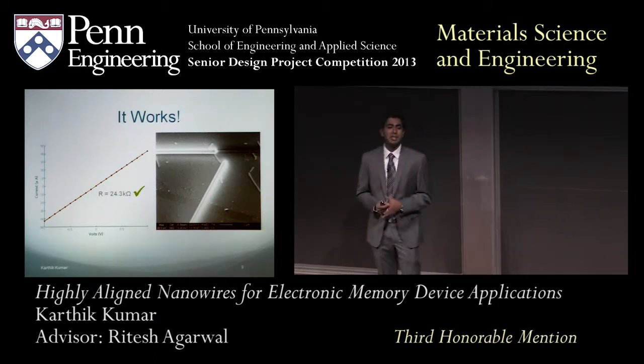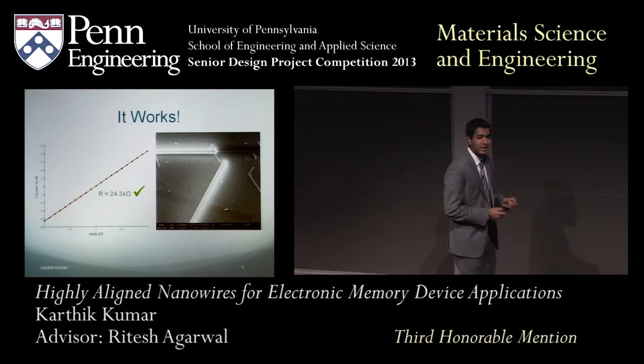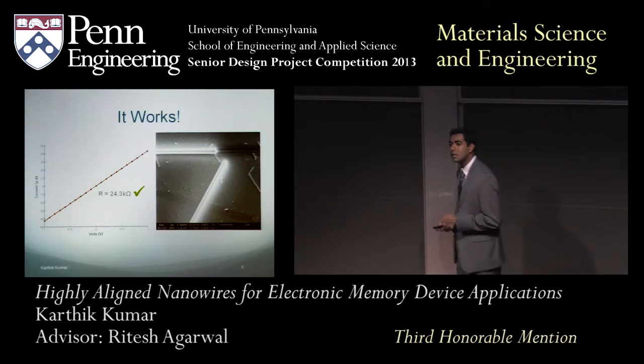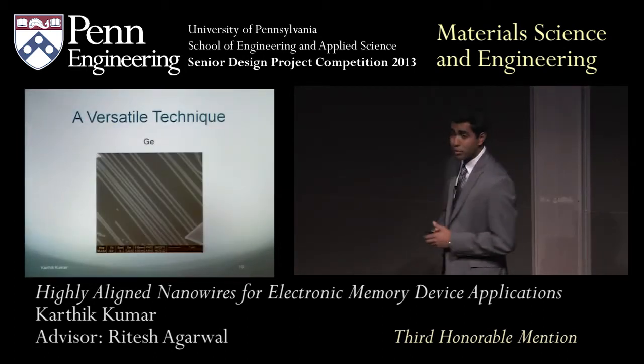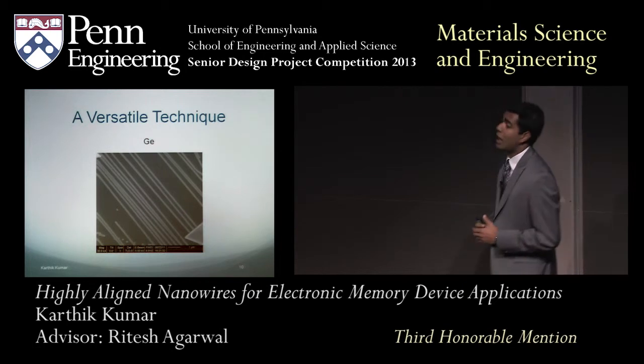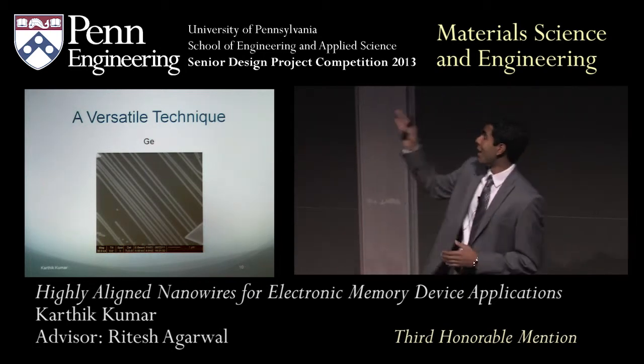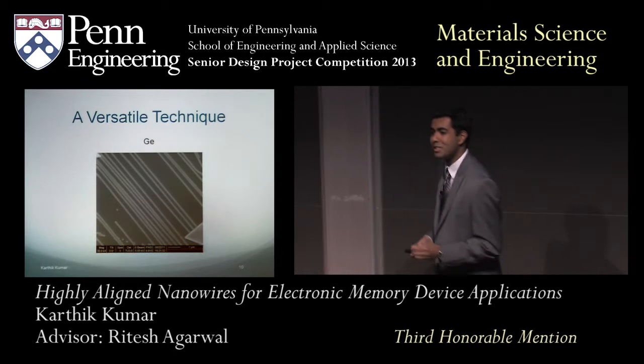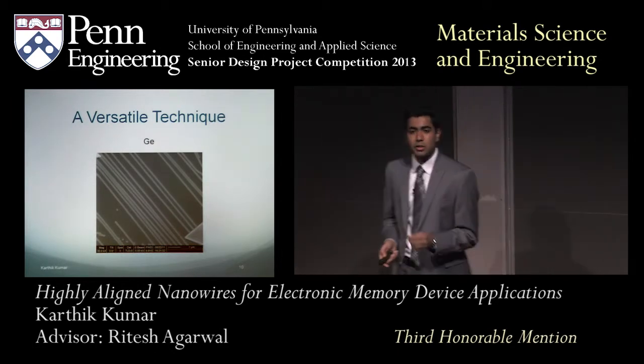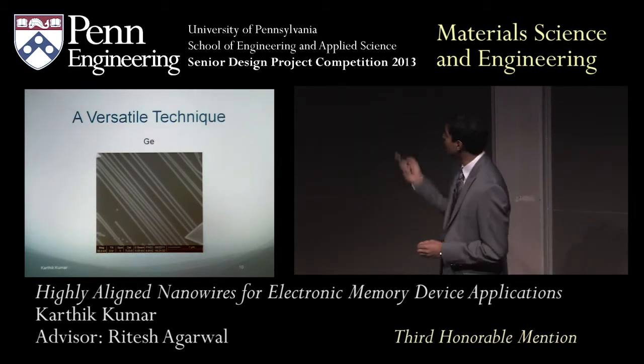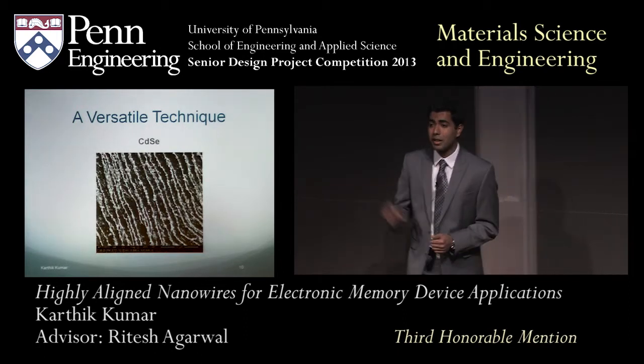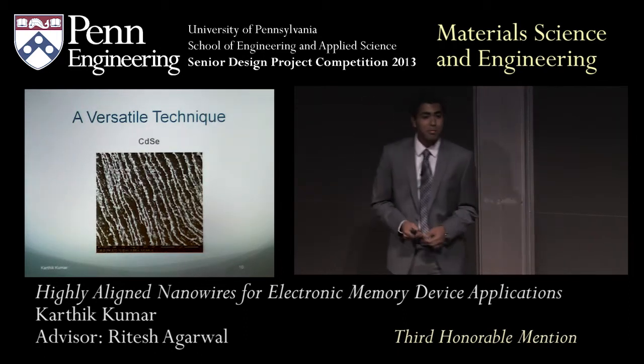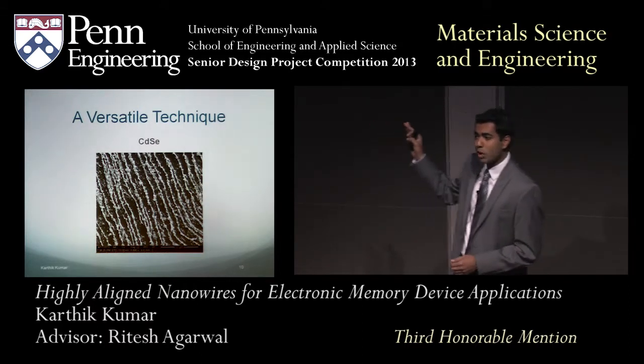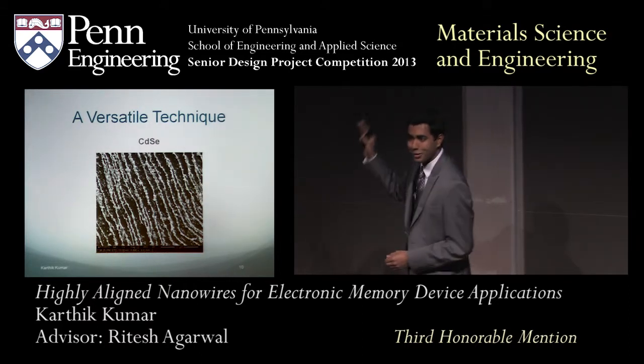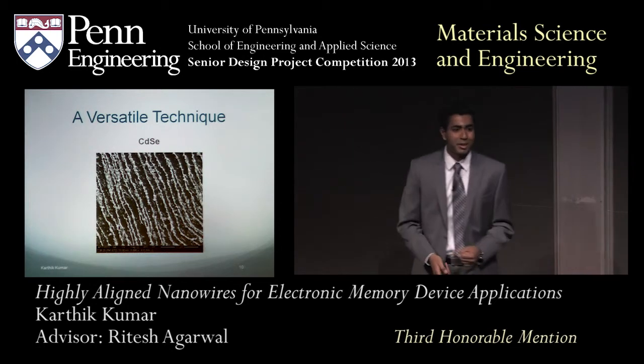Now, fueled by my success with the transfer process and the fabrication process, I wanted to see what I could do with this technique. A logical next material to try was germanium, and after optimizing the growth conditions there, we now have parallel-oriented germanium nanowires too. What about next generation photonic and plasmonic applications? Well, we have preliminary data showing cadmium selenide can be fabricated using this method as well. This requires a little bit more optimization.